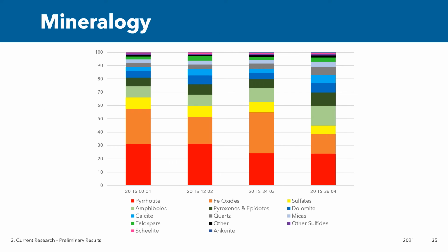Mineralogy of the initial samples was investigated before any testing occurred to establish a baseline. Modal mineralogy by SEM with automated mineralogy shows the 2020 sample is dominated by pyrrhotite and iron oxides. Dolomite and calcite are present, but at substantially lesser quantities than pyrrhotite. Scheelite is also present in all of the tailing samples.